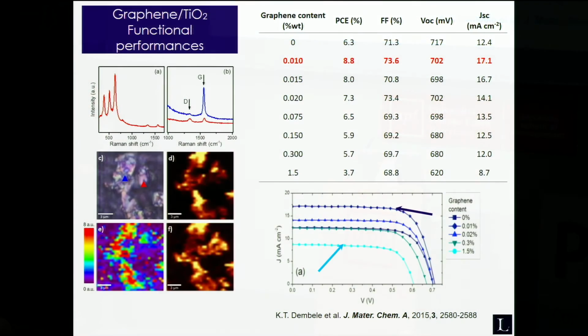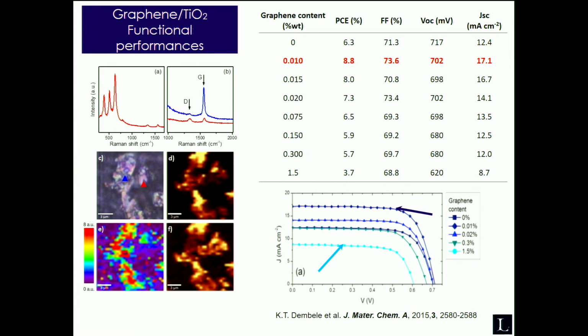People didn't believe us that graphene was still in the system after high temperature annealing at 500 degrees. So we applied two-dimensional micro-Raman to get a clear picture of graphene sheets after integration into the titanium oxide layer. We got almost the same results as carbon nanotubes, going from 6.3 to around 9% photoconversion efficiency.